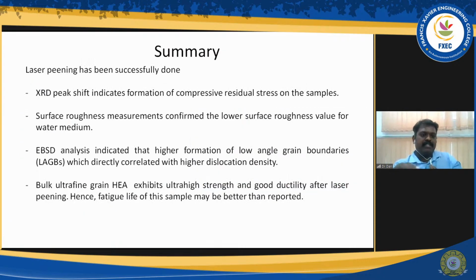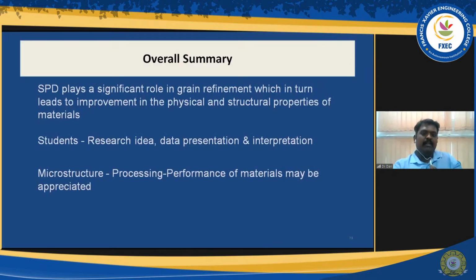Based on this study, from the XRD graph you can understand the compressive residual stress, and also how to do the surface roughness measurement. From the EBSD analysis, you can say that the formation of low angle boundaries can be directly correlated with the higher dislocation density in the material. So finally, the ultrafine grain size in this HEA is giving very good properties. That's what I want to conclude today.